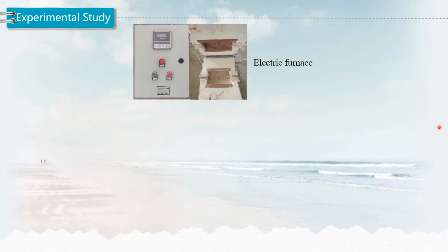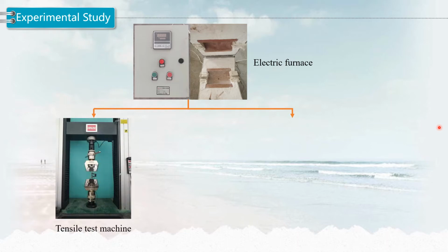Previous studies have revealed that high-strength steel loses strength and ductility after high temperature, and has inferior fire resistance due to its high thermal conductivity and low specific heat. As a result, fire can induce significant degradation of load-bearing capacity of hangers during a fire accident. Besides, hangers are also prone to fatigue damage, as they are subject to a large number of cyclic fluctuations induced by vehicles and the wind.